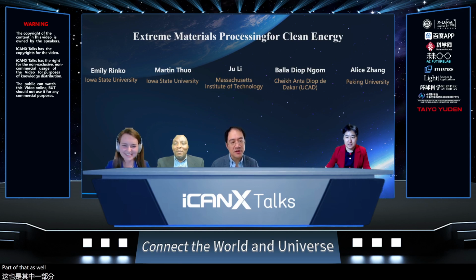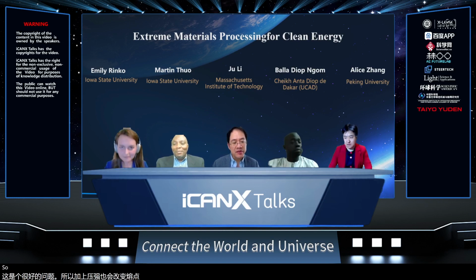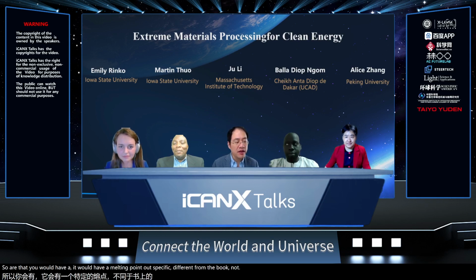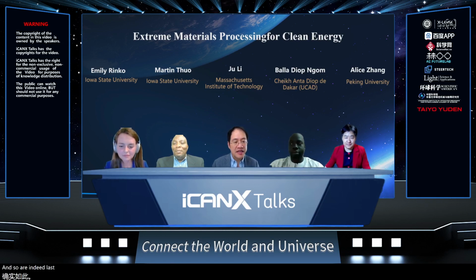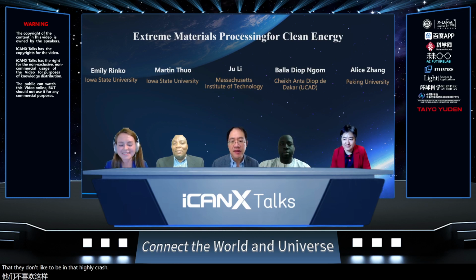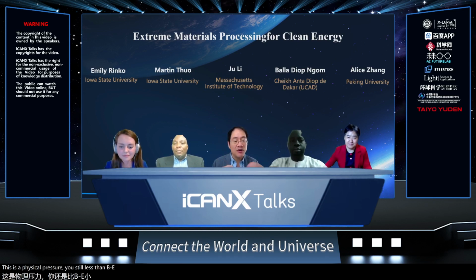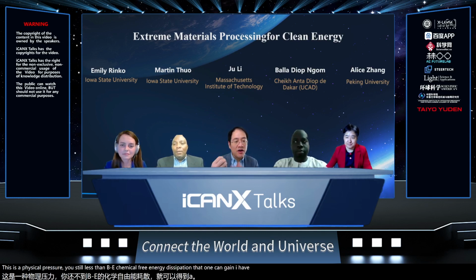That's a wonderful question. So this Young-Laplace pressure would also shift the melting point. So you would have a melting point that's significantly different from the bulk melting point. And so indeed, that's very significant. And that driving force actually would drive coarsening. They don't like to be in that highly pressured state. However, still, we did some order of magnitude calculation. This physical pressure is still less than the chemical free energy dissipation that one can gain by having more catalysis happening.